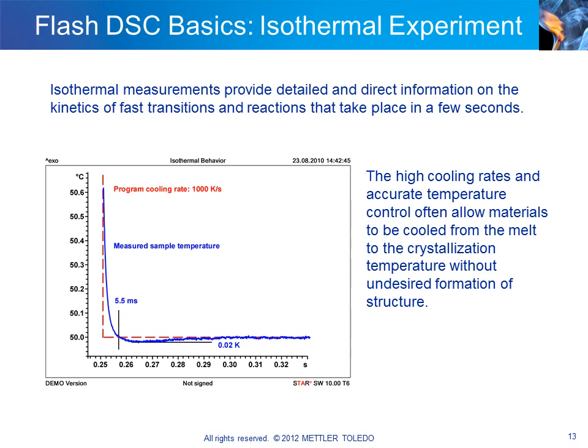Besides the need for high cooling rates, the transition region between the cooling and isothermal segment should be as short as possible. The diagram shows the curve of sample temperature in the transition region from a cooling segment at 1000 degrees per second to an isothermal segment at 50 degrees Celsius. In this example, the transition region of the Flash DSC-1 lasts 5.5 milliseconds. The maximum overshoot is 0.02 degrees.